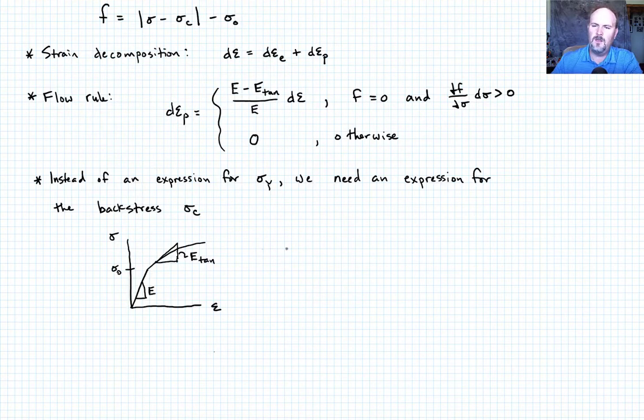So what we want to do is make an observation. Let's really quickly just draw the stress strain diagram for the load up here. So we have our elastic load up, we have sigma naught where it yields, and then we have an increase as we strain harden. So remember that now the whole surface is being dragged, so the amount that it's dragged must be proportional simply to how fast it's moving here along according to the tangent modulus. And I'll remind you here, this is e, the initial slope.